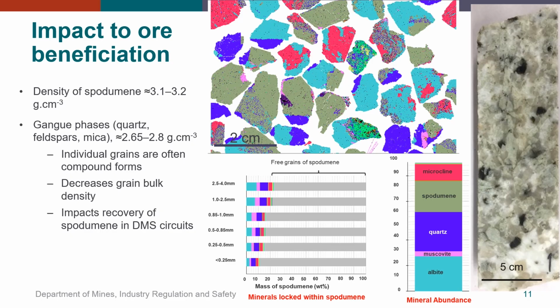So on the right-hand side, you can see an example of an albite spodumene pegmatite. This was crushed, sized, and polished mounts prepared of the different size fractions for automated mineral mapping, with a false color mineral map of a coarse fraction shown in the main image. From the mineral mapping, we can extract information on the mineral abundance in the sample and mineral locking properties of spodumene.